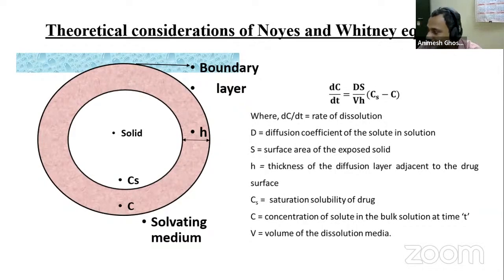In case of a polymeric matrix, what we generally do is increase the h value, right? Because we have added some polymer that will swell. Due to swelling, the path length, that means the thickness of the boundary layer, will increase, and the drug will travel that path. That will take time, and accordingly the drug will be slowly released. But if we can manipulate Cs minus C, where C is the bulk concentration, that means if we can change the Cs, then also we can control dC/dt, or slow down dC/dt. dC/dt is the rate at which drug is going into the bulk from the core or matrix. That is basically Fick's law, nothing else. If we can control the Cs, that is, reduce the concentration gradient, dC/dt will be reduced, and that will act as a sustaining action.